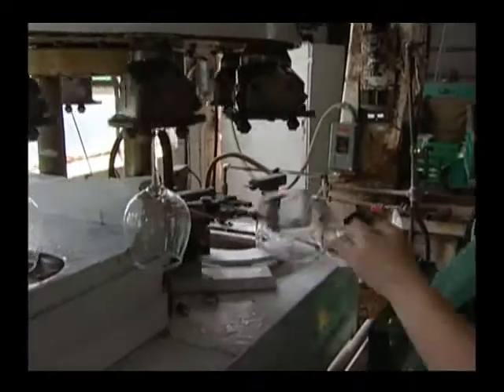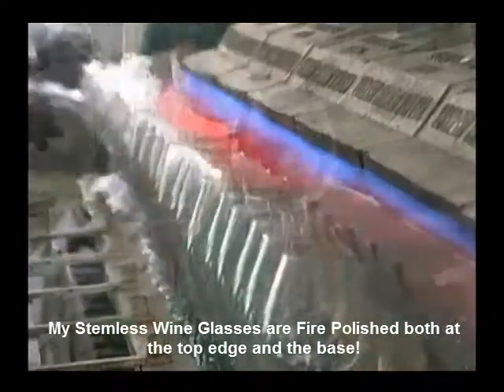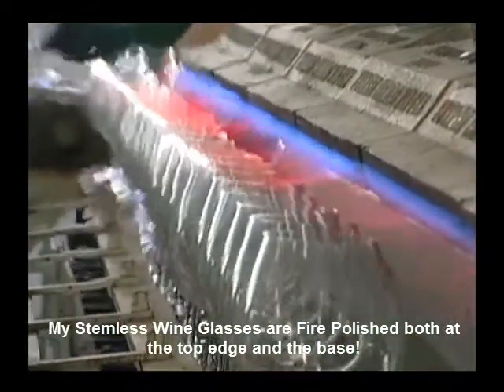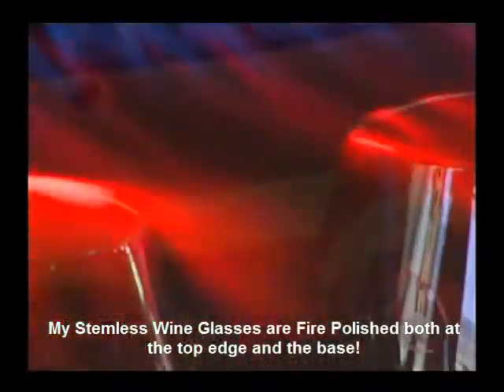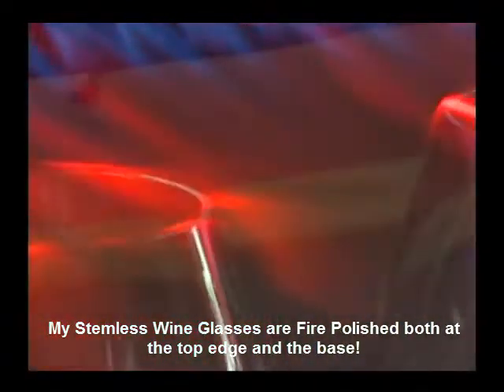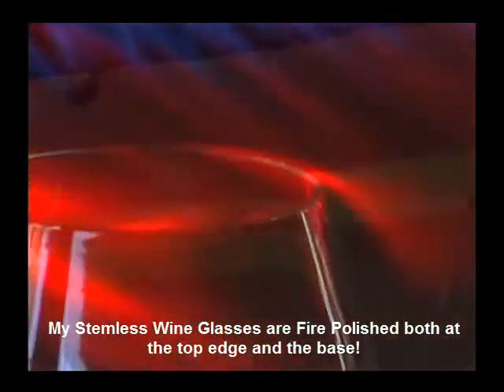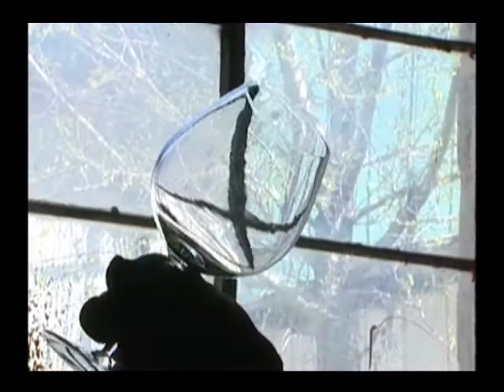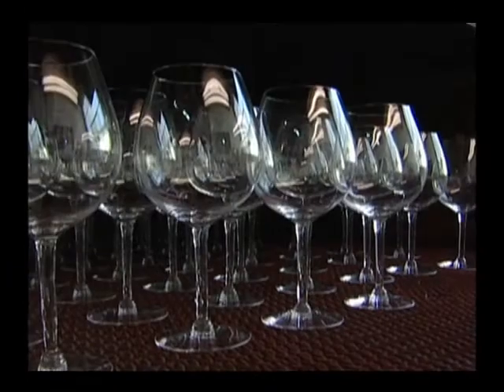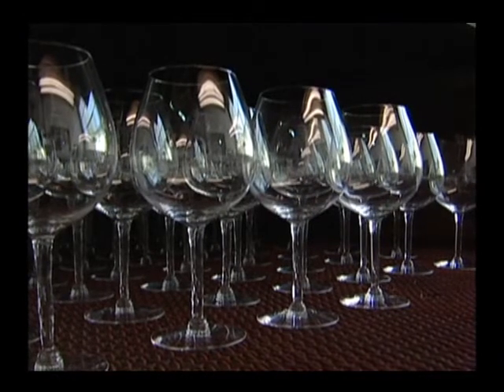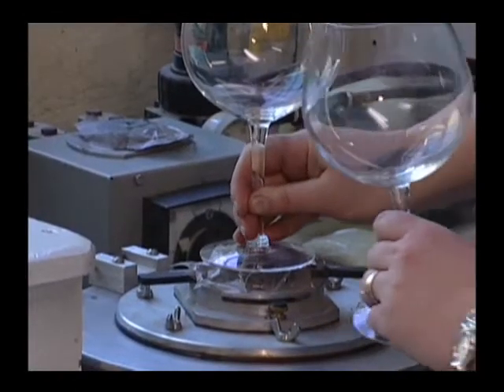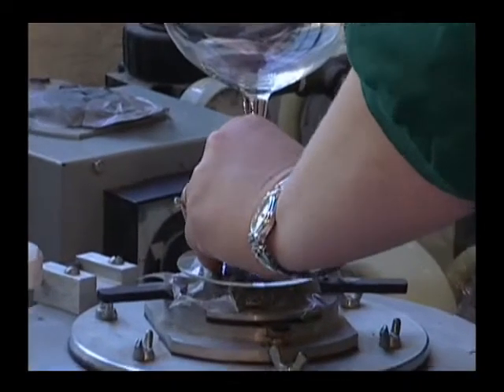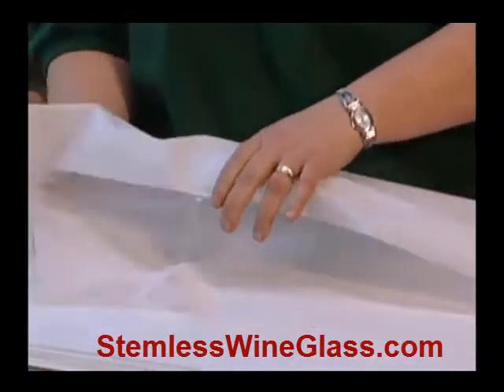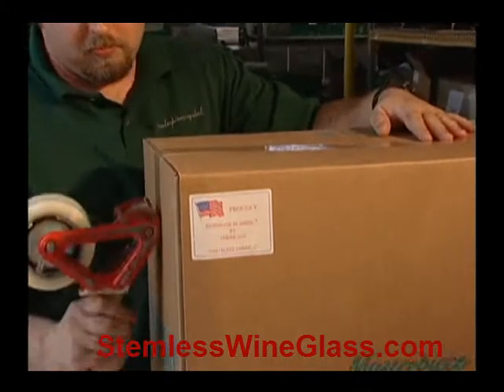The glass is inspected again, and if acceptable, is transported to the edge melter or continuous glazer, which fire polishes the top edge of the wine glass, restoring the shine and smoothing the sharp edges. After a third inspection, the glass is then placed in a re-annealing lehr for additional stress relief before final inspection and packaging. The Masterpiece Crystal logo is sandblasted on the bottom of the wine glass under the button and then delicately wrapped in tissue paper and packed for shipment.